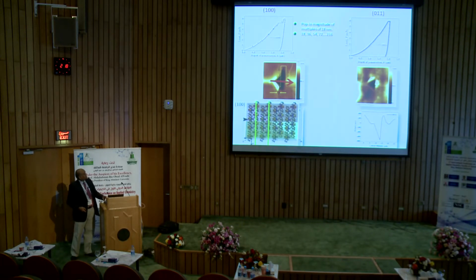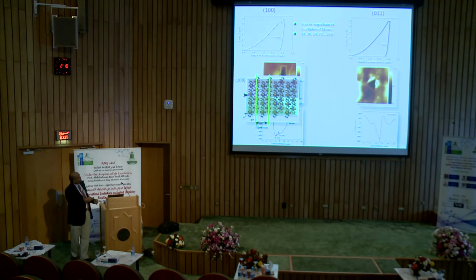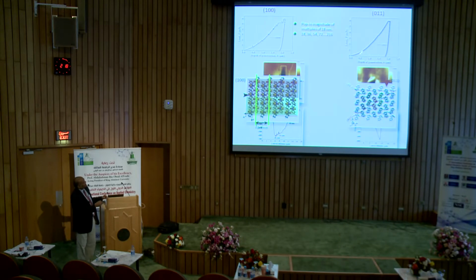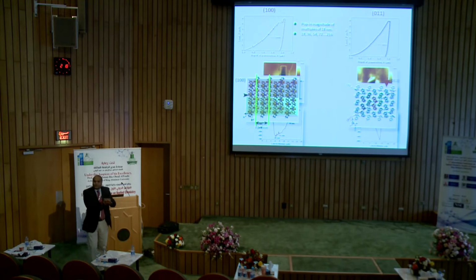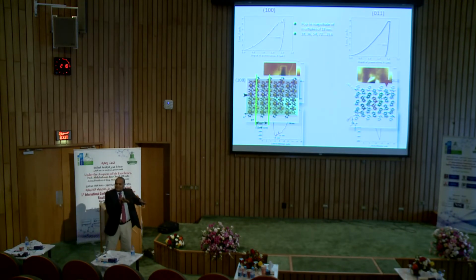Why is that? First and foremost, these differences come about because when we indent on the 011 phase, so we are indenting like this, the slip planes, the planes over which molecules can slide past, not molecules per se, molecular planes can slide past, are at an angle. So they can nicely slide past each other without much difficulty. That's why you get a very smooth response.